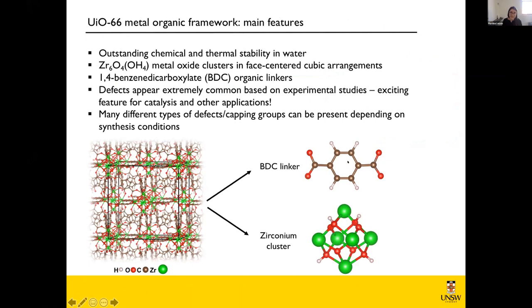Even if this is a very stable, very crystalline solid, it is very common to have some defects in it because some of these linkers might go missing. And if some of these linkers go missing, essentially what you end up with is some of these zirconium atoms, represented in green here, being undersaturated. And so whatever is sitting around will go and saturate those sites. This could be water, could be a chloride ion, could be another carboxylic acid. It all depends on the synthesis conditions. So lots of defects might be there, and the defects could be extremely different.